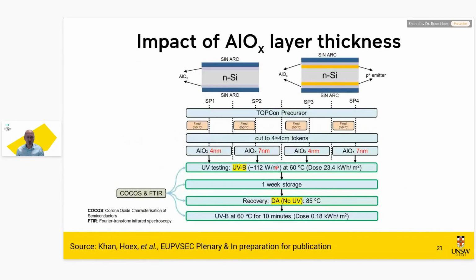So we set up quite a complicated experiment, and I will not bore you with all the details, but we take two types of samples. One is a more conventional lifetime sample that allows us to do more sophisticated measurements, particularly to extract DIT and fixed charge. And we take a sample that is representative of the front of the TOPCon solar cell. Then we again test firing versus non-firing, and we test two different thicknesses of ALOX. These are ALD ALOX films, 4 nanometers, which is more representative of what people would use in industry nowadays, and 7 nanometers. And then we use accelerated testing using UVB, because that gives us the result very quickly.